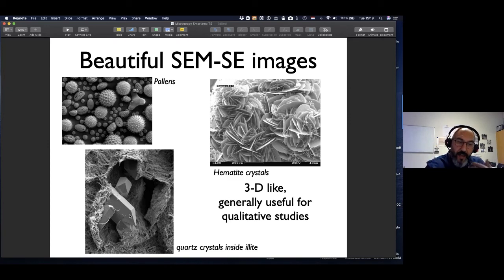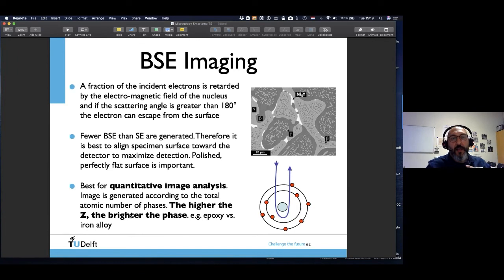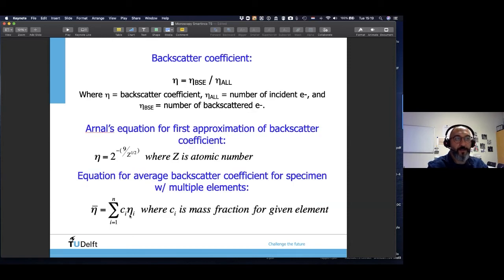So that's the reason I really advise you guys, everyone, to concentrate on BSE imaging as much as possible, because it gives you 2D compositional images so that you can do image analysis, perhaps a compositional analysis. Then you can say I have 50% of phase gamma and, I don't know, 25% of phase beta and so on and so forth. Some stereological analysis you can do. I think it's far more useful for us to do BSE imaging and analysis if we want quantitative information.